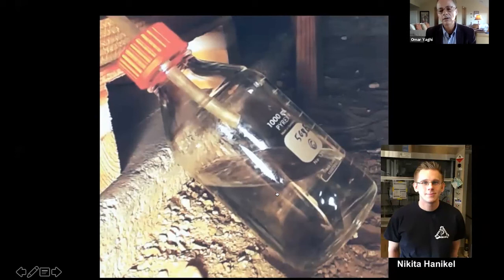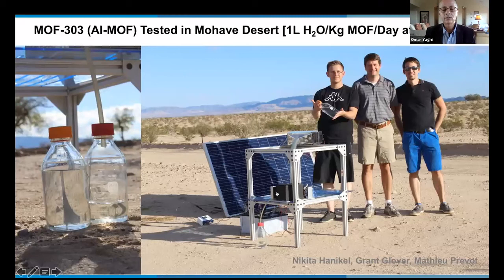1 liter of water per kilogram of MOF. And you see here the water being harvested in real time. These are droplets. I hope all of you can see that. Well, if you are able to take the water in and out with great facility, then it should be possible to do many cycles during the day with, let's say, a solar panel to supply power for the fans that would push the air into the MOF.